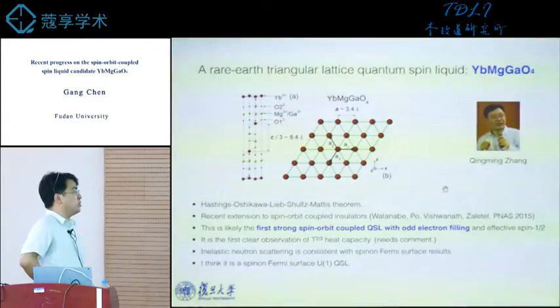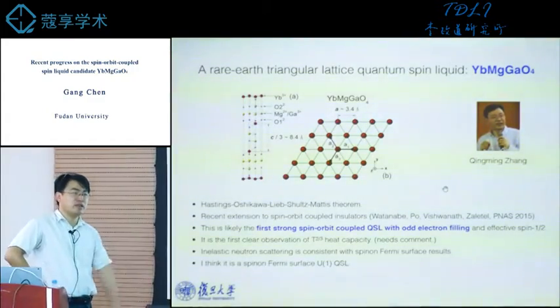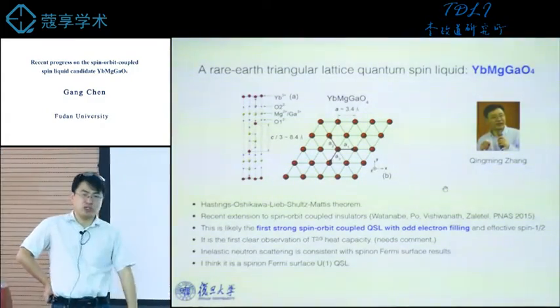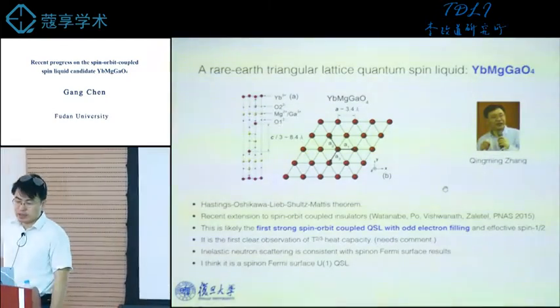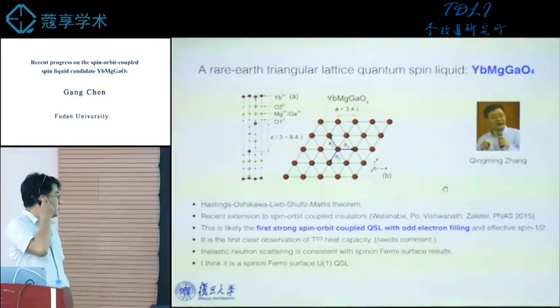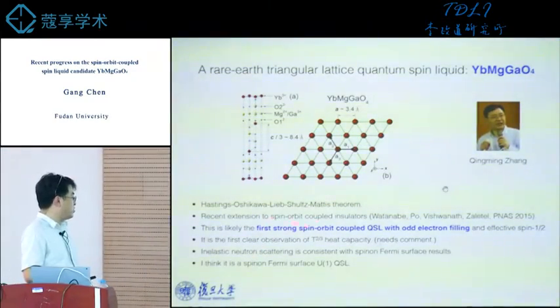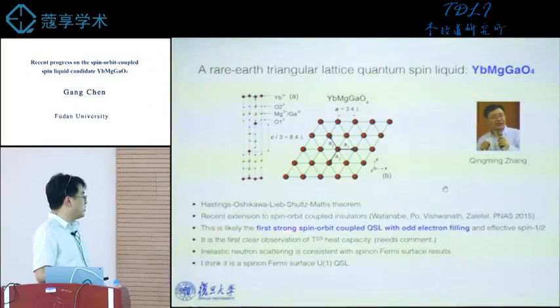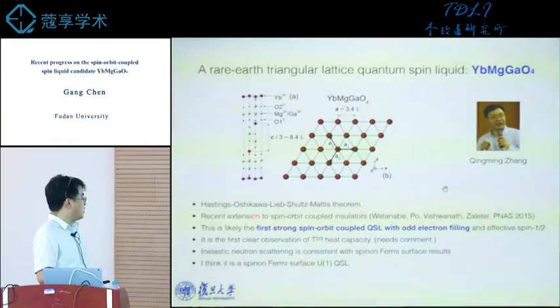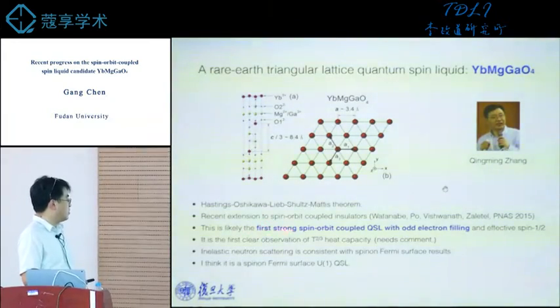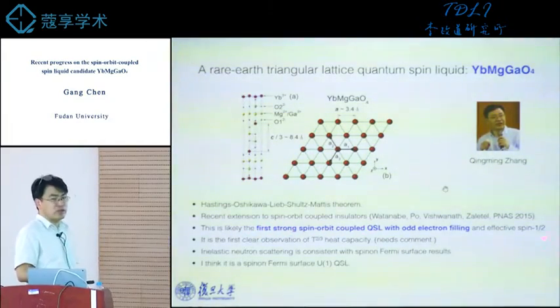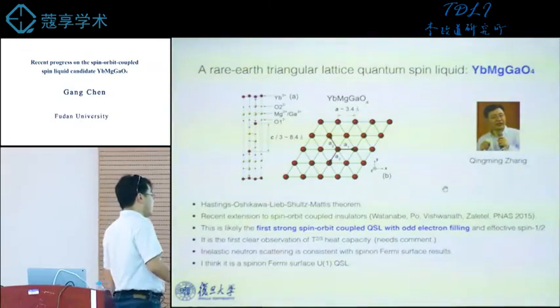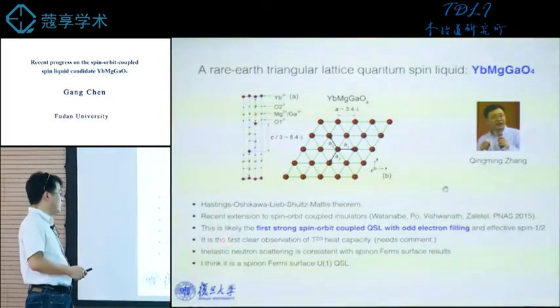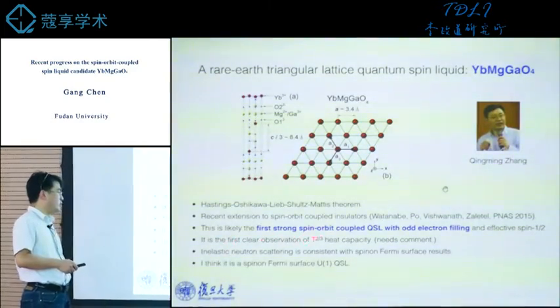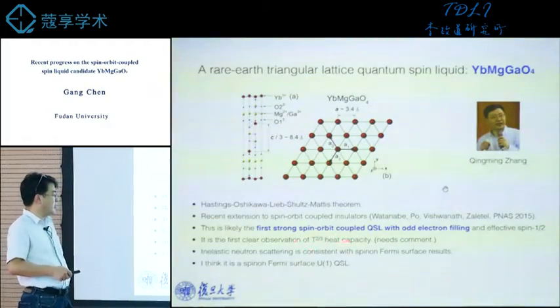So the system has to be exotic just by observing the thermodynamic measurement. We can make such a claim, right? So that's what we propose, together with Qingming Zhang and other people. We propose that this is the first strong spin-orbit coupled quantum spin liquid with odd electron filling and effective spin 1/2. So this is also a first clear observation of this behavior.